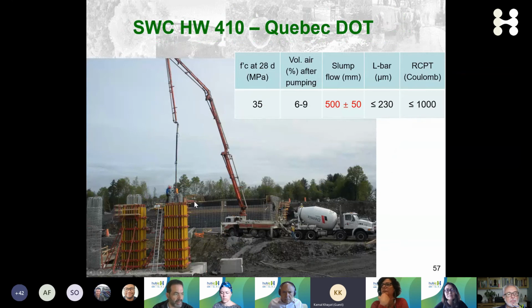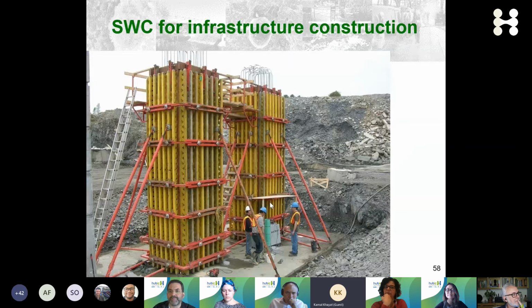In our industrial chair at the University of Sherbrooke, we teamed up with our DOT and our industrial partners, designed some concrete that were implemented in a bridge. And you can see here the slump is not 650 plus or minus, it's 500 plus or minus. The design strengths, the durability, everything is the same as high-performance concrete.